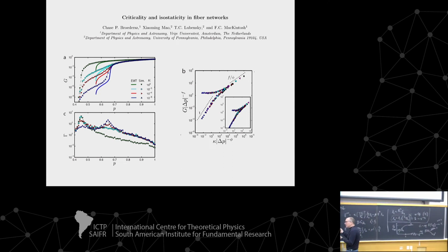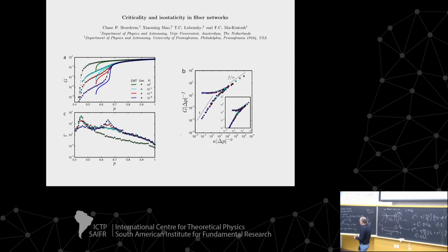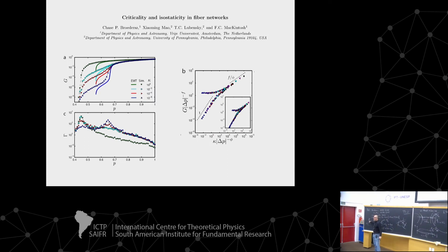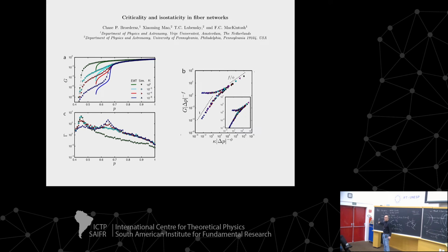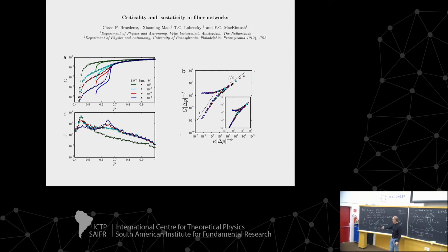If it's t equals 0, they're not thermal fluctuations. Those fluctuations are these non-affine deformations, okay? Now, I suspect you've seen in some of the prior lectures, actually, Andrea was sort of hinting at it. She was mentioning non-affine effects. These non-affine effects can look like a fluctuation, but they're static. And they're actually only in response to an applied strain.